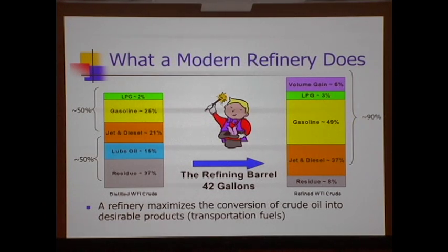The diagram on the left is a bar chart of what you would get if you took some West Texas Intermediate crude and just distilled it under atmospheric conditions. Okay, and you would look at the very bottom of that. You get about 37% residue, or an asphalt-like material. You only get 25% gasoline, number one and number two fuel oil, about 20%. Unfortunately, that is not what is needed in the marketplace.